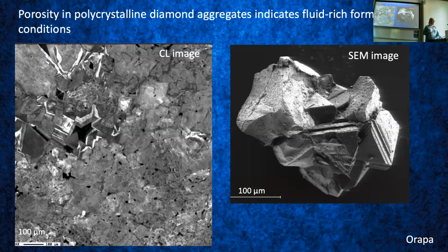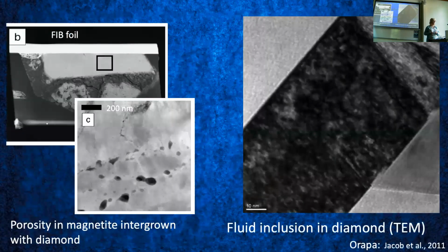So it's not just the pores between the diamond crystals, but also pores in the inclusions. They have inclusions in the diamond crystals, but they also have minerals intergrown with these diamonds, like this garnet here. We studied mostly the stuff that's intergrown with the diamonds, because you have a lot more material there, since the diamonds are so small. Clearly the inclusion is even smaller, so you are very limited there. So we concentrate often on these intergrowths. And these intergrowths can be all sorts of things. Here it's a garnet. It can also be magnetite.